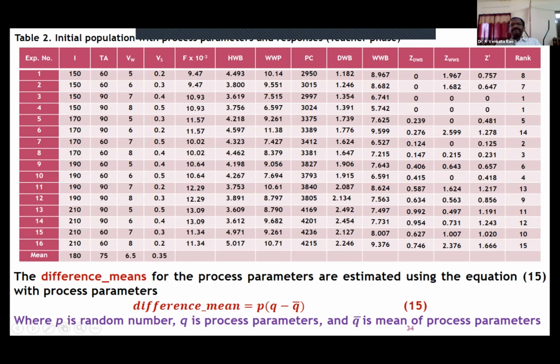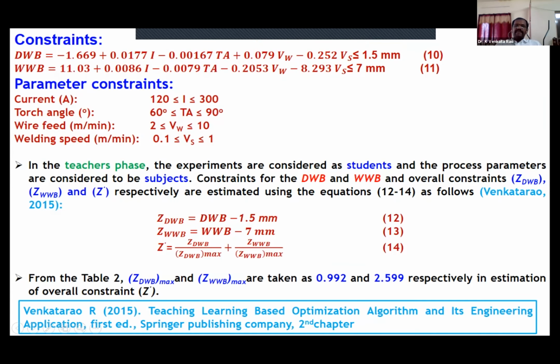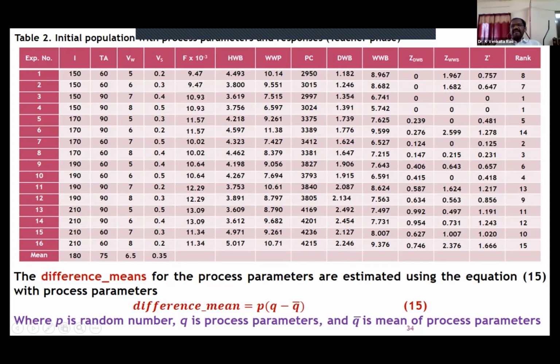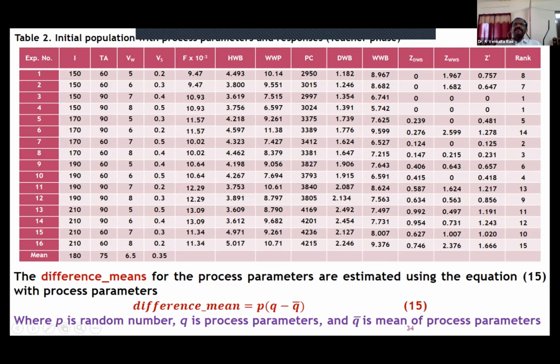Similarly for the width. For experiment 1, the experimental value of width of weld bead minus 7: 8.967 minus 7 gives 1.967. Similarly for the third one, 6.741 minus 7 gives a negative value, which was taken as 0. Here also the value is less than 7, so we have taken 0. Whatever negative values we got were taken as 0, and positive values were fine as they are.